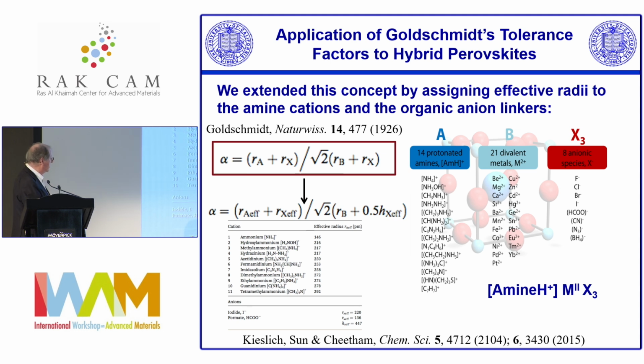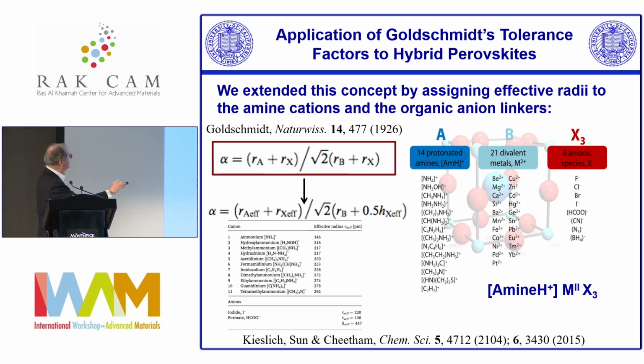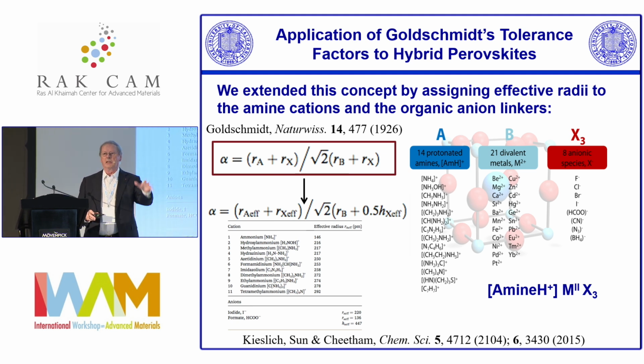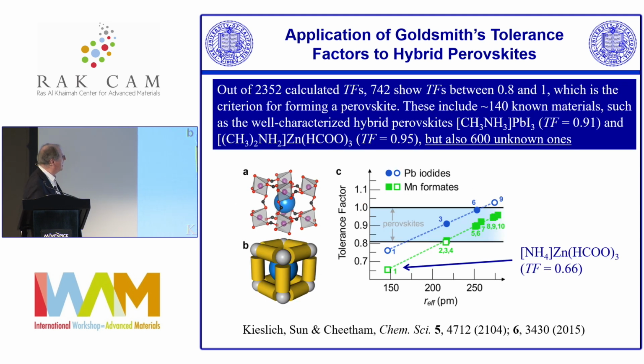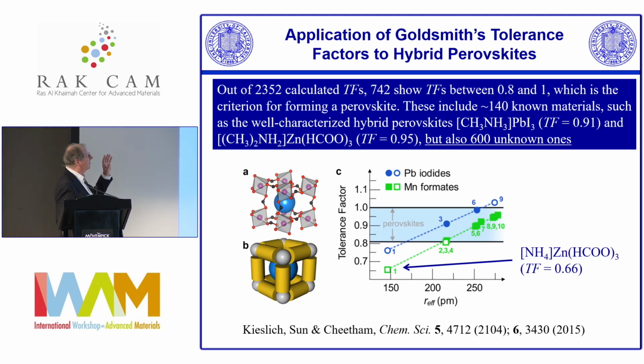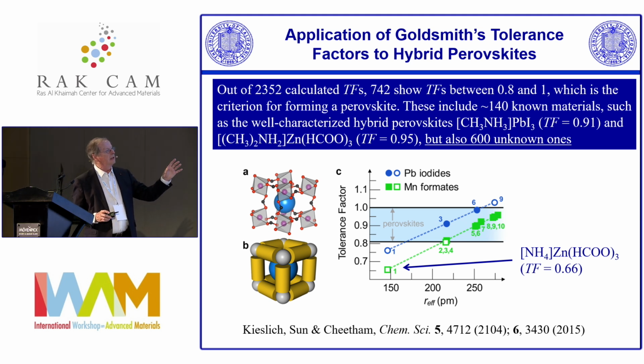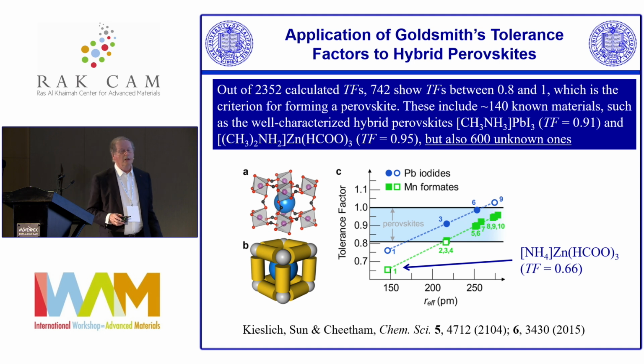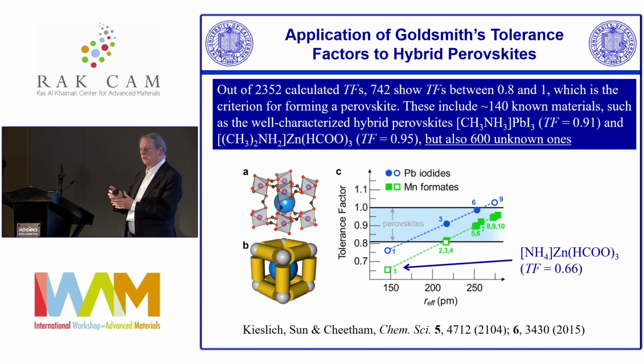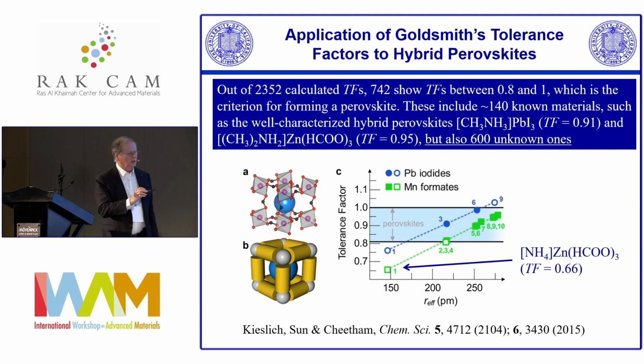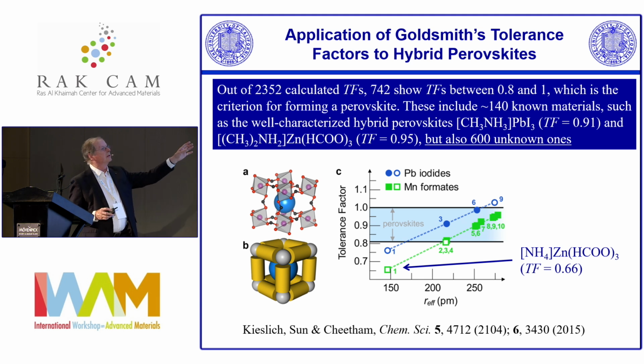What we did with Gregor Kieslich and Xi Jing Sun when I was at Cambridge was simply to extend this to hybrid systems. So we had to assign radii to all the amine cations and other cations, and assign sizes to the cylinders of things like the formate, so we treated those as cylinders. And this worked remarkably well, not only for the metal ammonium iodides and the formates that we were working on, but for a lot of other systems, as you know, like the ones that Matt was just talking about. So this is a very useful tool.